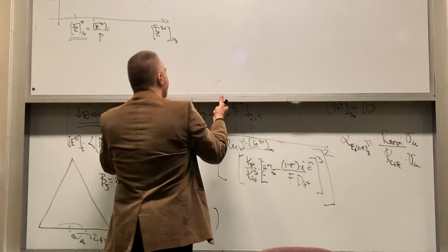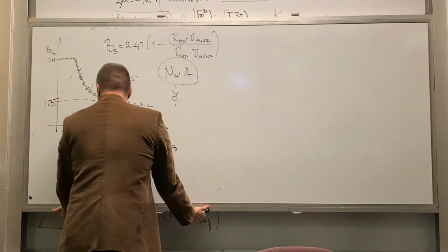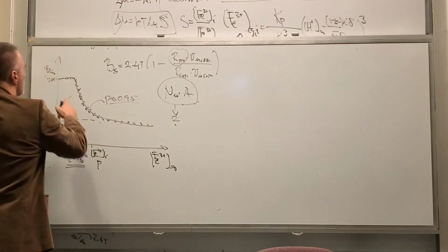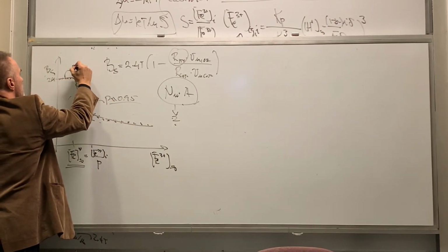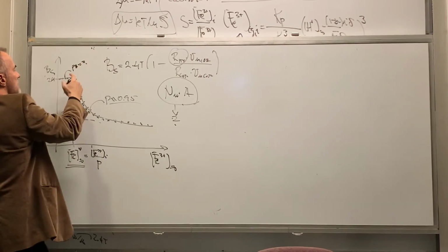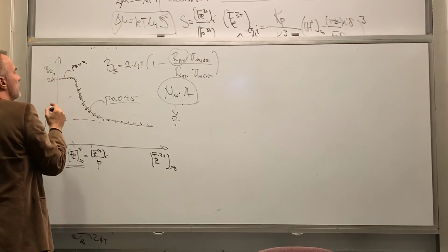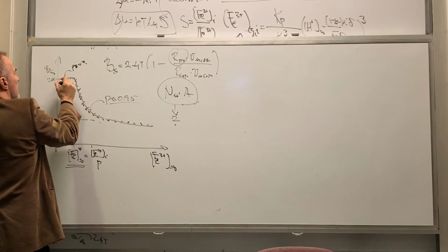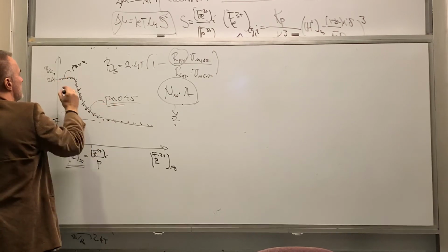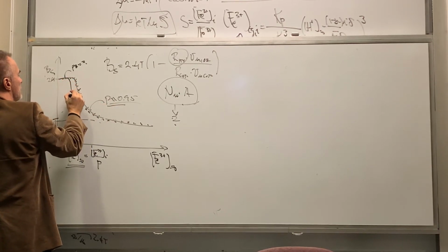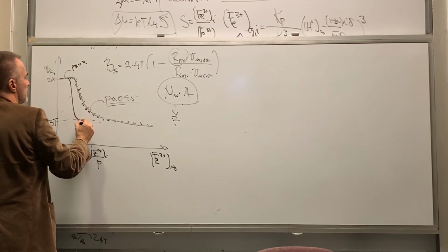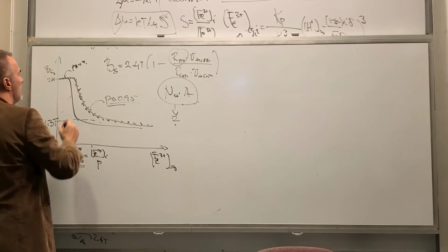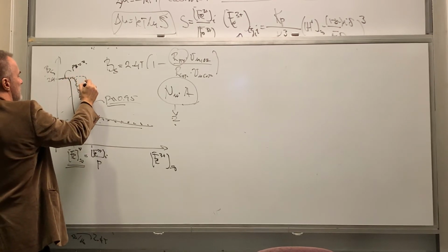What it really means is this. I can have a look at how this looks. If this is, for example, for pH equal 2, how is this going to look for pH equal 2.1? I can calculate using this same thing. And for pH 2.1, it's going to look like this. For pH 1.9, it's going to look like this.